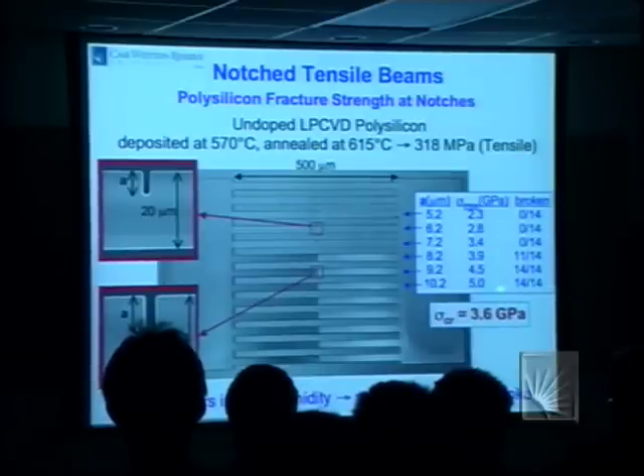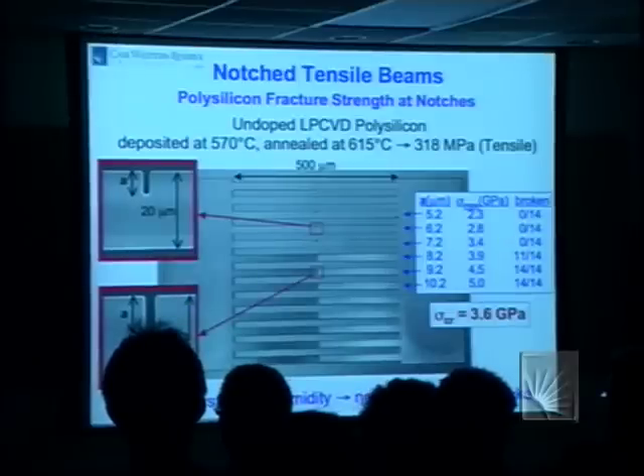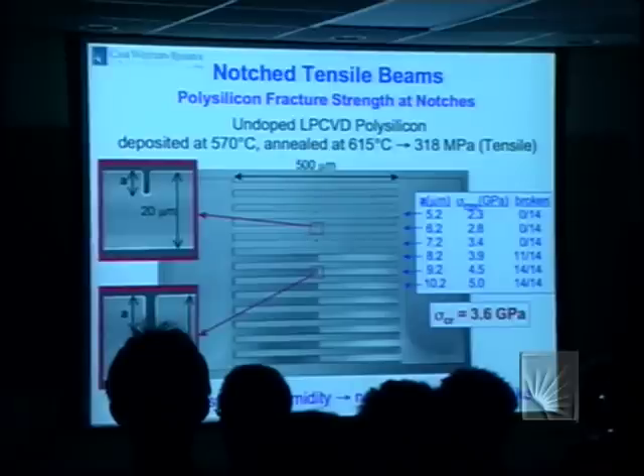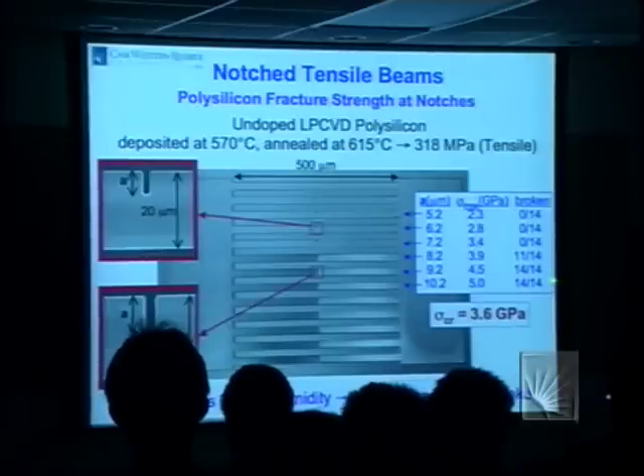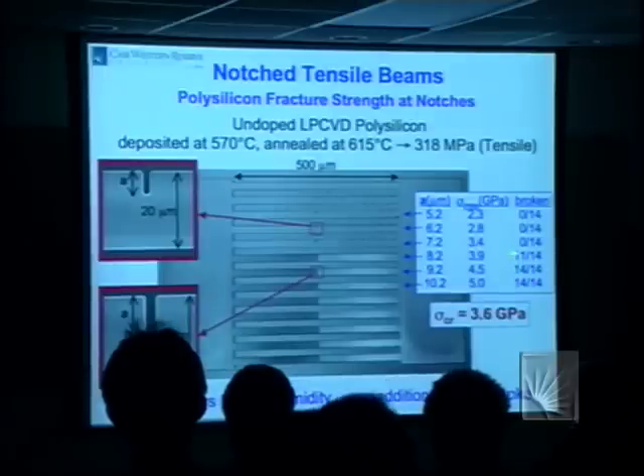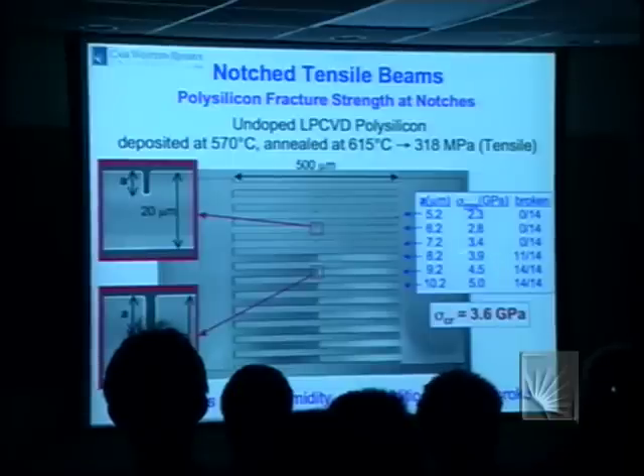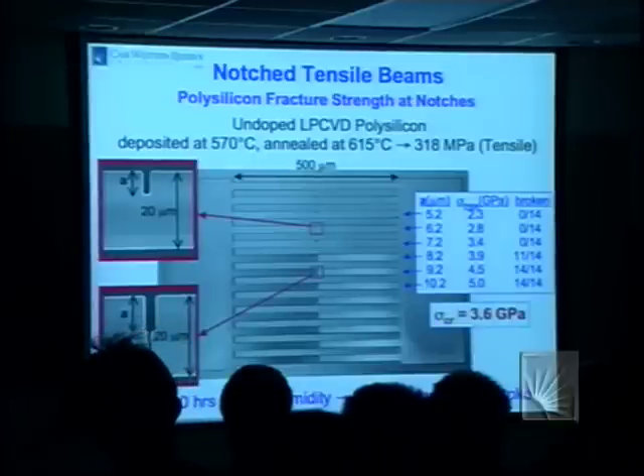We made 14 devices. That's another thing about MEMS. You get statistics very, very easily. If you wanted to make 100 such devices and you want to spend some time at a microscope getting better and better statistics, it's not hard to do. But you can see that in this device, all notches of this depth failed. No notches of this depth or smaller failed. And a subset of notches with this depth failed, and so we could determine the strength at 3.6 GPa.